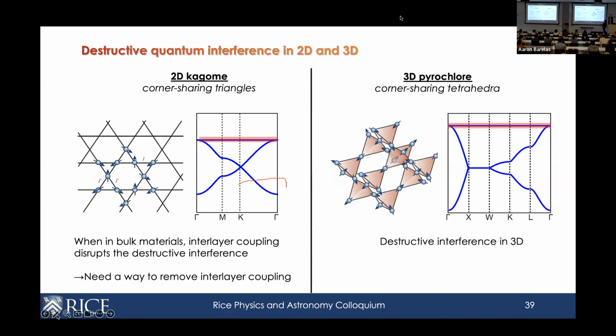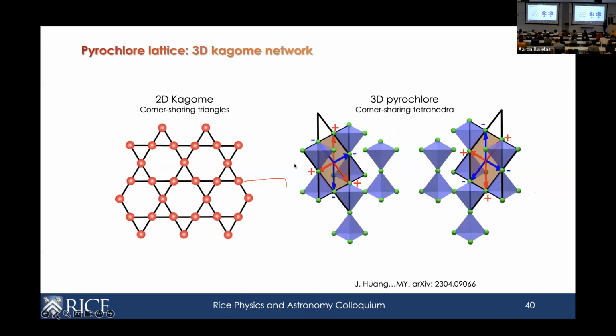So what do we do? We have to find a way to remove this interlayer coupling. And the way to do that is by going to 3 dimensions and finding materials where the out-of-plane hopping is also removed because of this quantum interference effect. And that is a pyrochlore lattice. Okay. And the way to see that is the following. If you take a pyrochlore lattice, you can cut it in such a way that you can expose a Kagome lattice like this. You can do that in 2 ways.